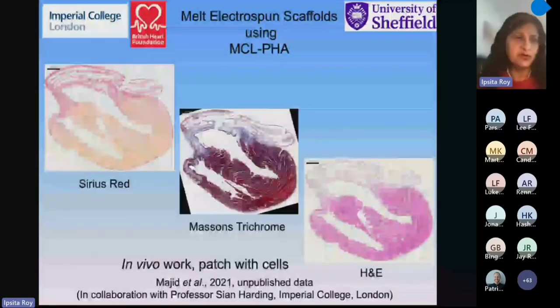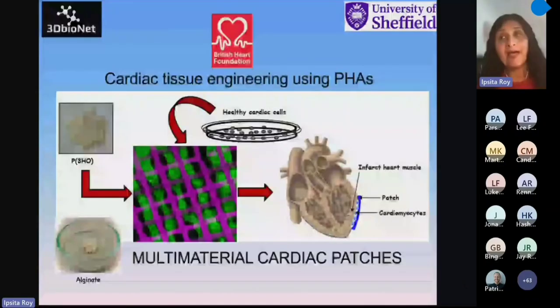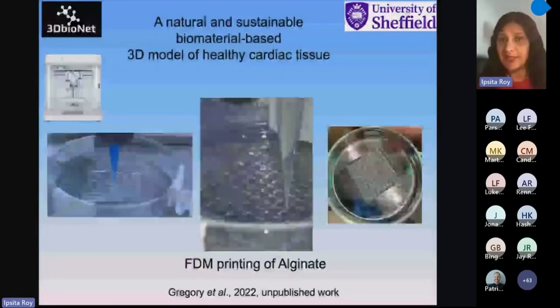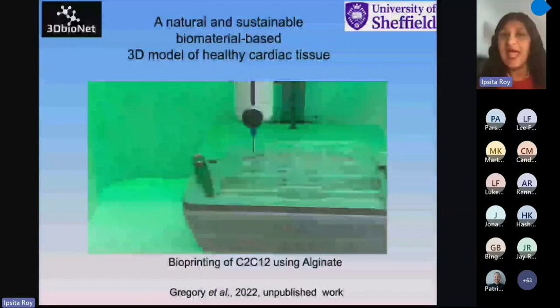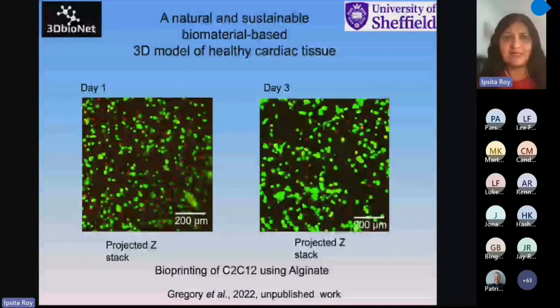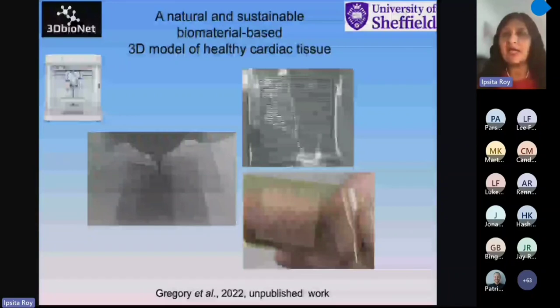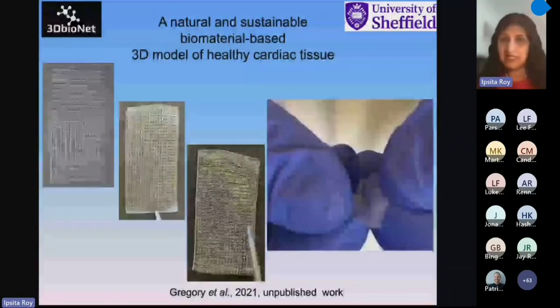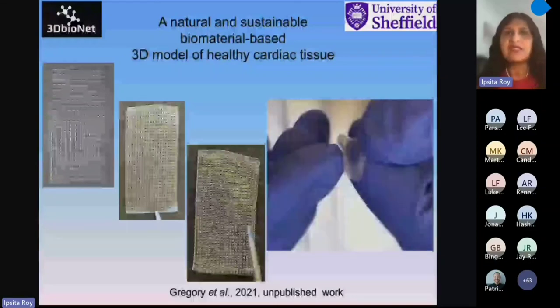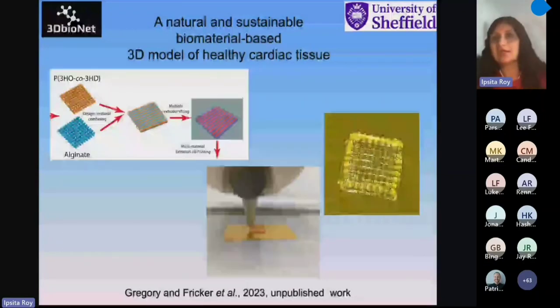Just briefly touching on this, I won't be able to go into the details. We've now done what is called a multi-material cardiac patch. Here, we encapsulate the cells in alginate and bioprint them, so we are printing these cells with alginate. And you can see here the cells beautifully tolerate all this torture of going through a nozzle, and we get lovely green cells. We've optimized this. Then we use the medium chain length PHA as a kind of support for the alginate, otherwise it falls apart when we put it onto a heart. So this is a typical cardiac tissue patch, and this is the multi-material patch, which is alginate and PHA.